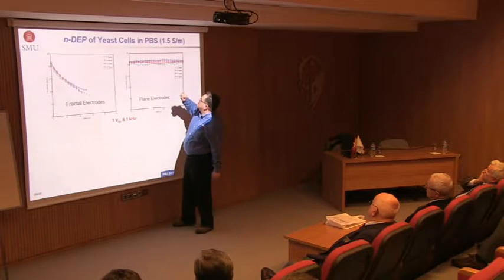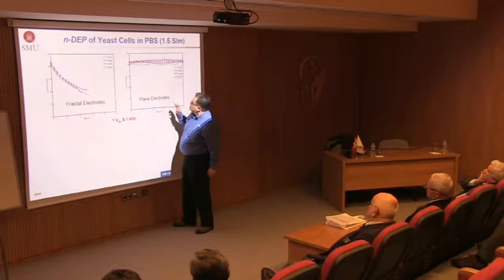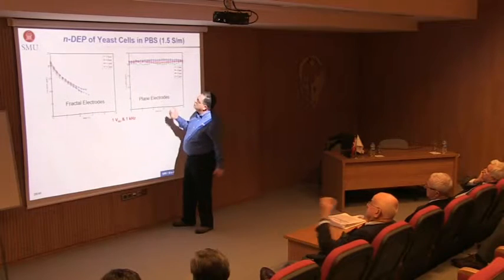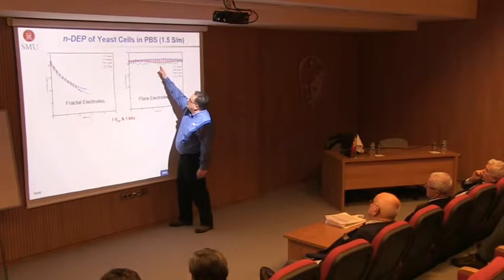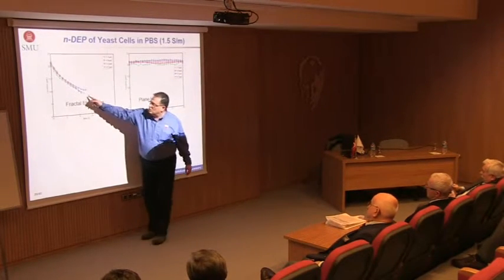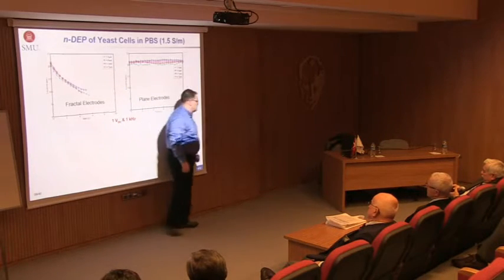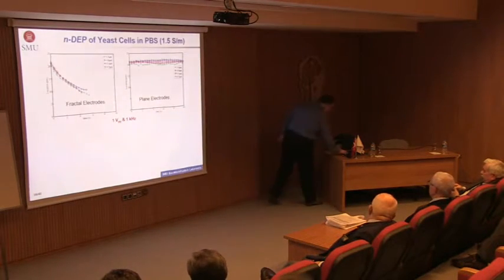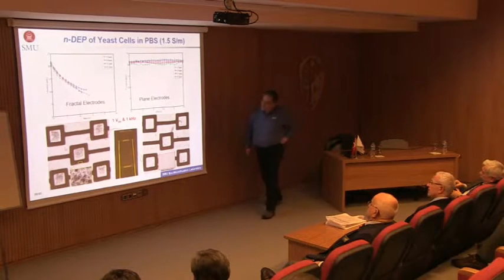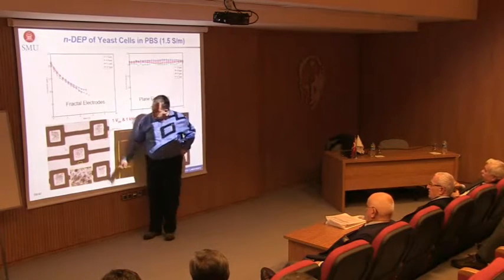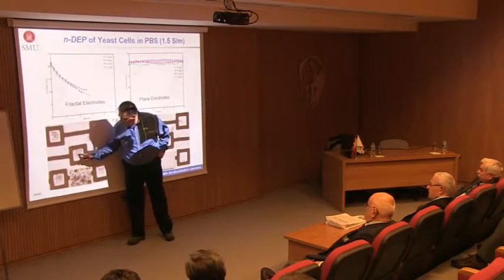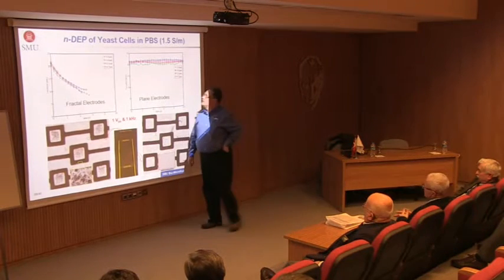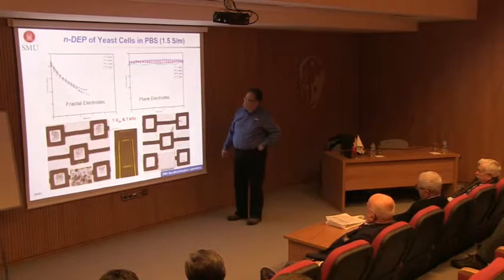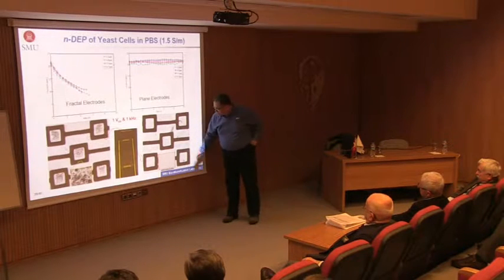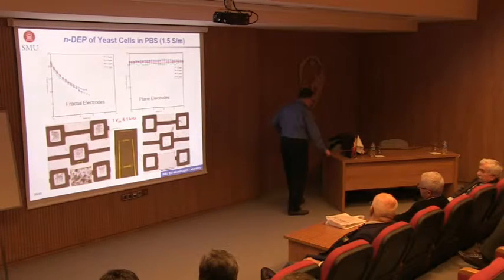So for the case of plane electrodes, we have found different particles. These are yeast cells at the edge of the electrodes, and I expect them to move, but they don't in high conductivity medium, but they do when you're in the fractal electrode system. And the proof of it is below. Using fractal electrodes, negative DEP worked. We can actually concentrate the yeast in PBS, which doesn't work with plane electrodes.